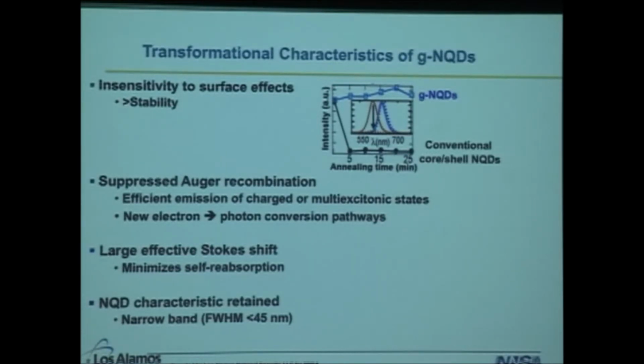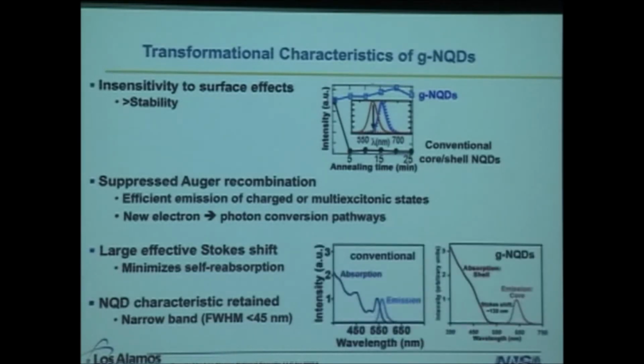So that shows that potentially one could actually remove ligands in the giant dot case and still have activity. In addition, of course, we can suppress Auger recombination. And I didn't mention this before, but in the giant dot case, we have a large effective Stokes shift. So you minimize self-reabsorption in your devices.